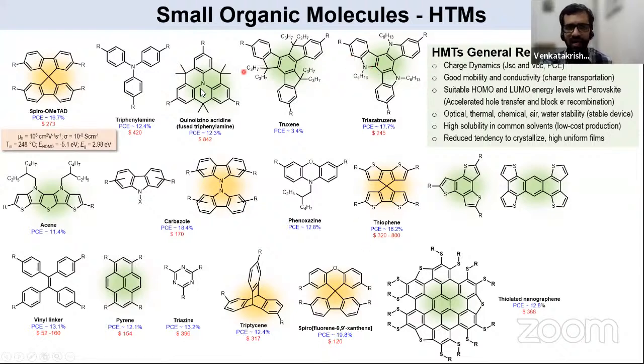Okay, but on the other hand, if you look at the planar structures, well, they are planar, highly conjugated, so one can, in principle, bring in the pi stacking, and hence the charge transporting pathways can be enhanced. But on the other hand, morphologically, they don't give very uniform, smooth films actually. So that is the problem with these pi conjugated structures, whereas these structures have low hole mobility because they don't allow pi stacking. But on the other hand, they have beautiful amorphous character. How do you blend them together, right? So that was the question we were asking.